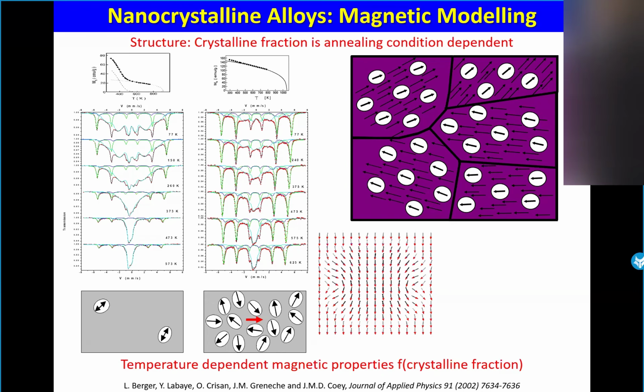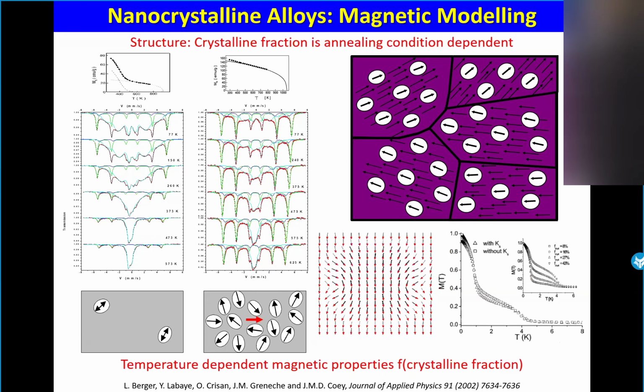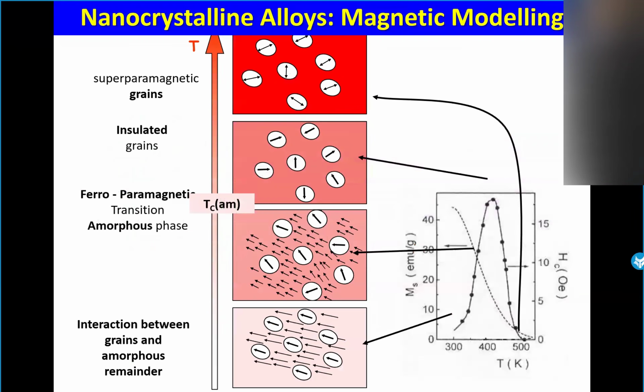And we made also some computer modeling to check the presence and the thickness of this grain boundary. And the grain boundary we obtained was exactly of the same order as the grain boundary observed by Monte Carlo simulation. And we have also different cases here. And this was able to provide us information. At low temperature, strong magnetic interaction within the amorphous matrix, within the grains, and strong interaction between grains and the amorphous matrix.